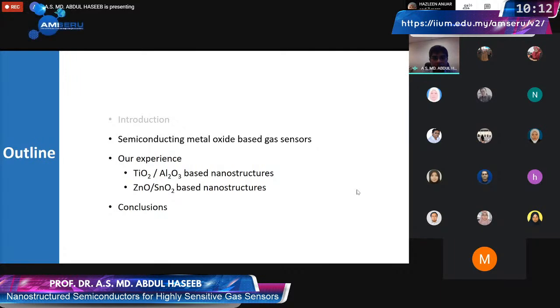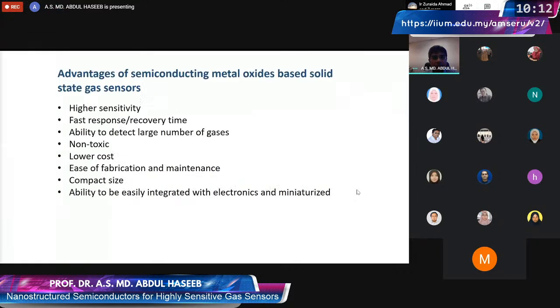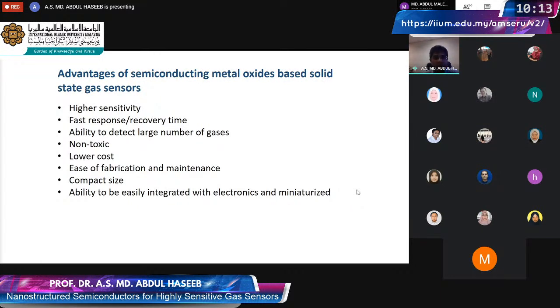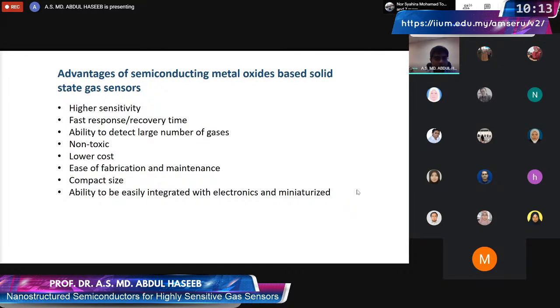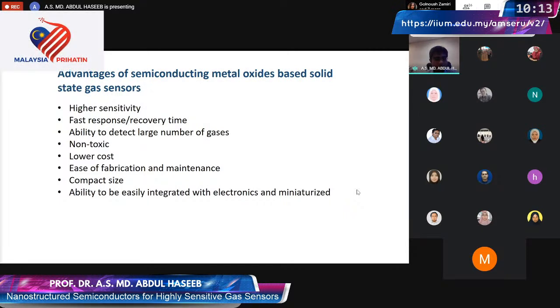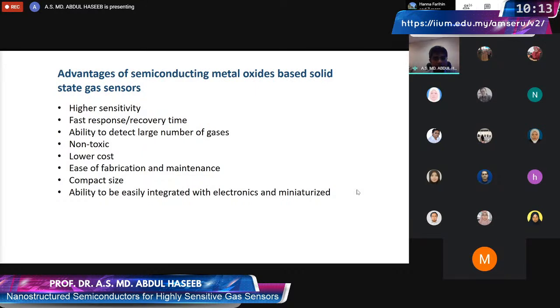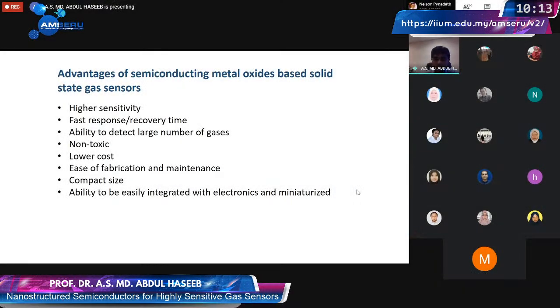So what I will try to give you now is an overview of these metal oxide gas sensors in general before we share our experience. Metal oxide based gas sensors have a lot of advantages. They have high sensitivity. They can respond quickly compared with other sensors to different gases. They can detect quite a large number of gases. They are non-toxic in nature. They can be produced at a lower cost with an easy fabrication process. They can be made really small in size. And above everything, these gas sensors work on the principle of what we call chemi-resistive, which means that they change their electrical properties when a gas interacts with them. And as a result, since it deals with electrical quantities, they can be easily integrated into electronics and miniaturized.